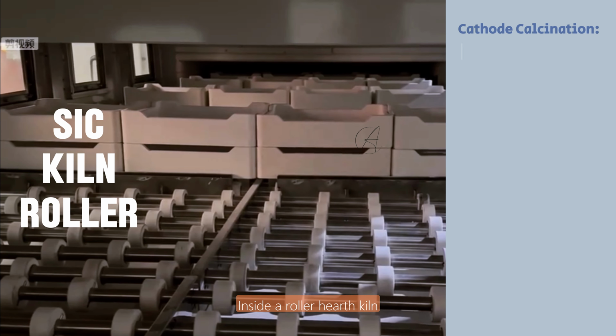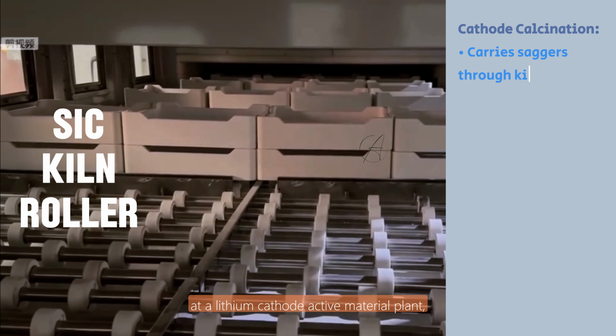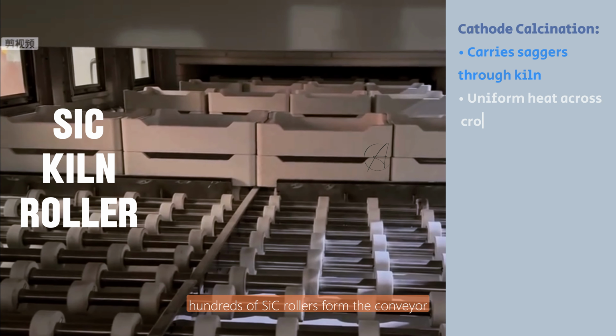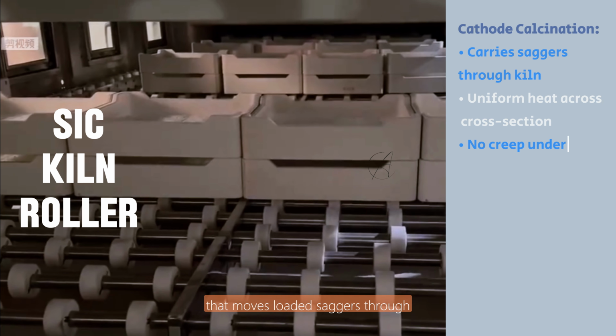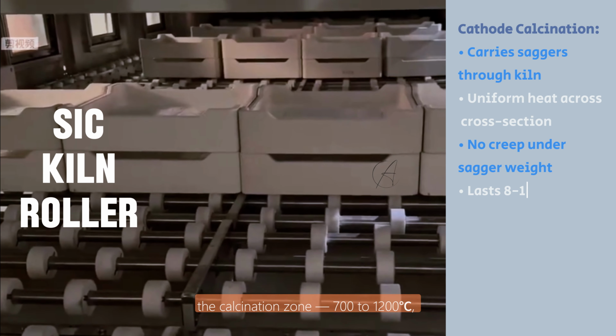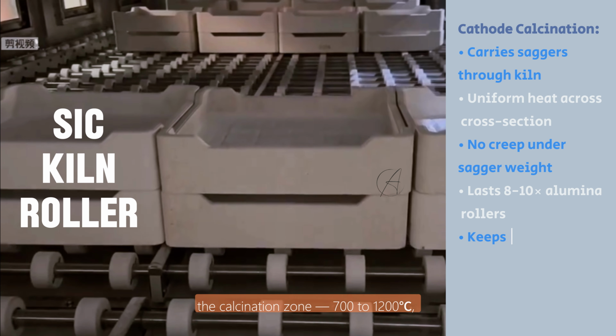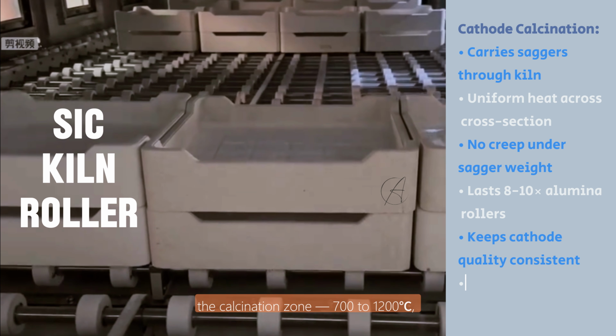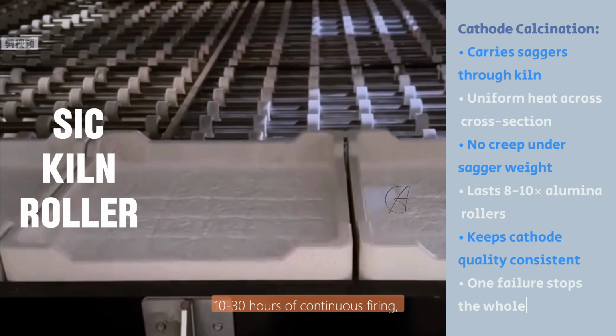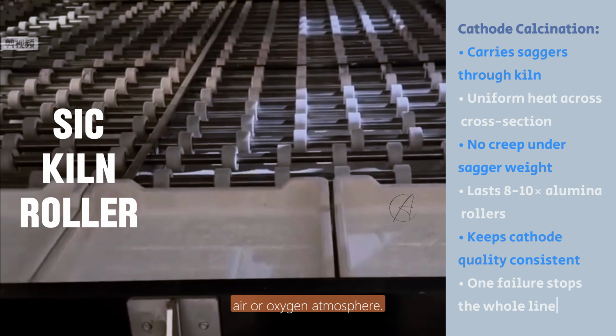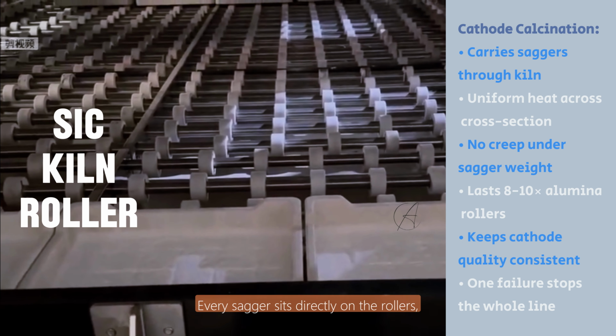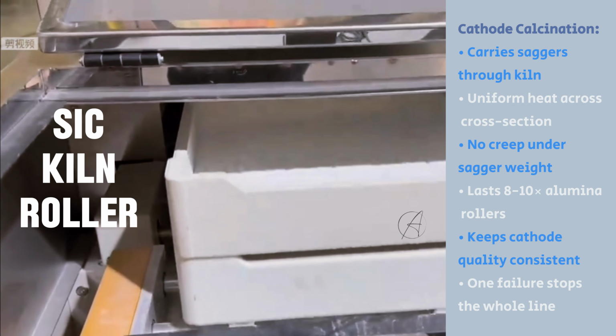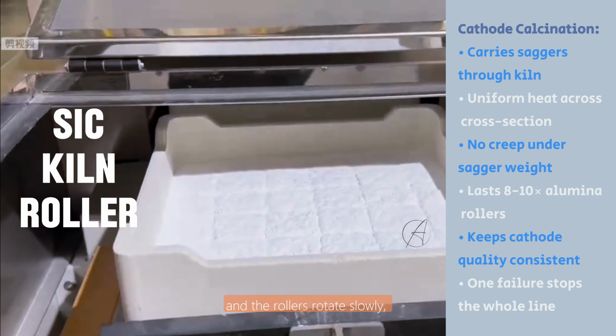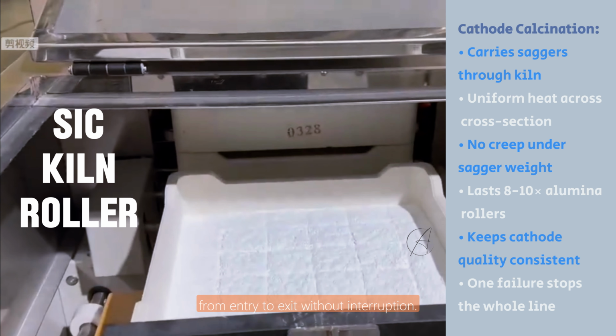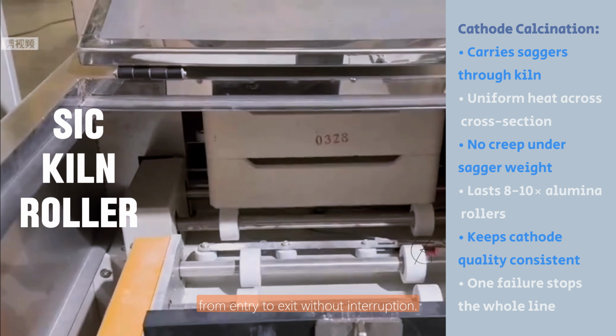Inside a roller hearth kiln at a lithium cathode active material plant, hundreds of silicon carbide rollers form the conveyor that moves loaded saggers through the calcination zone, 700 to 1200 degrees Celsius, 10 to 30 hours of continuous firing, air or oxygen atmosphere. Every sagger sits directly on the rollers, and the rollers rotate slowly, advancing the entire batch from entry to exit without interruption.